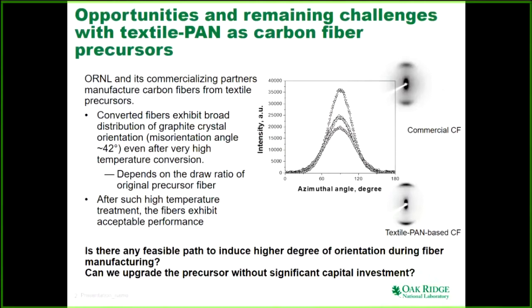If we look at the X-ray diffraction pattern in the background image, the top one is a commercial fiber and the bottom one is a textile PAN based fiber. The two lobes up and below, and the white line going there, is the beam stopper. That's how the X-ray goes through, the fiber stays here, and that's the image plate collecting the image. The two lobes up and below are the 002, the graphite diffraction peak, and how broad that peak is tells us the orientation factor in the carbon fiber. Orientation factor in the carbon fiber is critical.